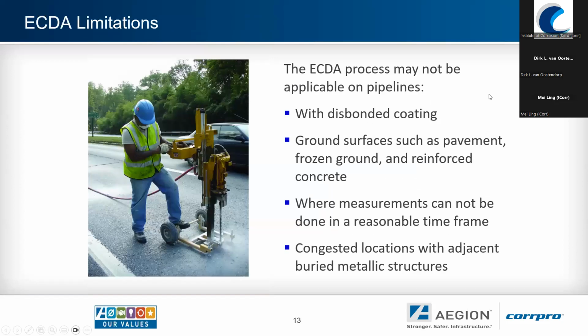So as with any good tool, we do know that there are limitations. And this was one of the discussion points with the federal regulators when we were going through the assessment of the process. In cases where there are disbonded coatings, external corrosion direct assessment struggles very, very much so, because the disbonded coatings will then isolate sections of the pipeline, and there is no way for any of the overline techniques to be able to identify defects at those locations. Another area is where the surfaces, if you have pavement or reinforced concrete in areas where there's frost, the use of standard techniques like CIPS and DCVG and even some of the electromagnetic techniques suffer, so the accuracy is compromised. They're not possible.